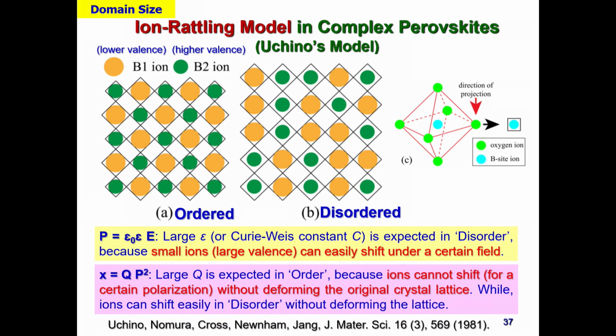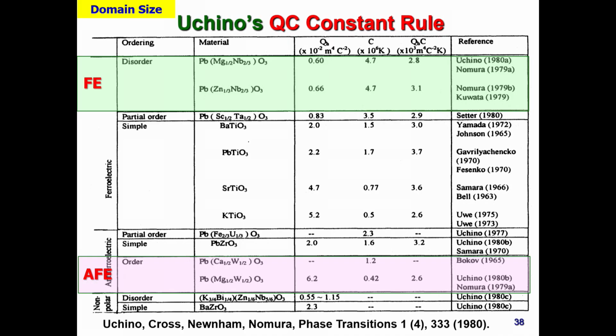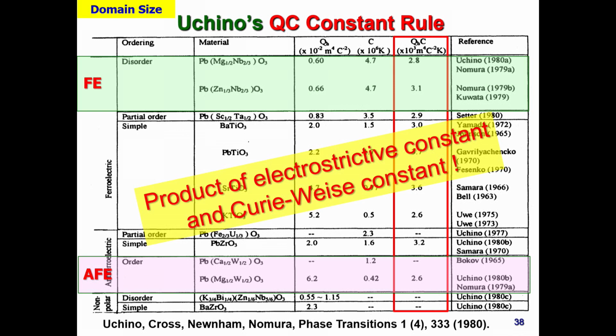To the contrary, ordered materials, to create a large displacement, Q values, electrostrictive constant, and to create a certain polarization without making a big distortion around the frame, we cannot make any polarization. Therefore, large Q is expected, large C is expected. Therefore, we tabulated lots of samples for the ferroelectric, antiferroelectric, nonpolar, all, and the electrostrictive constant and the Curie-Weiss constant is really measured. So these are large and small, one order of magnitude difference. This is also one order of magnitude difference. But if you make a product of electrostrictive constant and Curie-Weiss constant, this is beautifully around 3, plus minus less than 5%, okay? So again, we are waiting for some physical theoretician to explain this constant rule, okay?